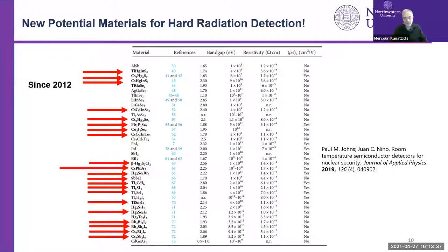And in this article, there's a long table of recently found materials that are promising for X-ray and gamma ray detection. And the materials marked by the arrows are our materials from our group. And we have some basic properties. The band gaps are great. These are the band gaps, which are suitable. The resistivity is suitable. The mobility-lifetime product sometimes is known, sometimes is not, but it's also promising. So now basically we cracked wide open the materials field. And from here, we can select materials for further investigation. That's not enough because we have to investigate them at a deeper level to see if they actually work.